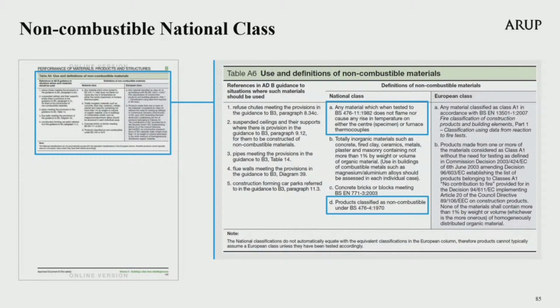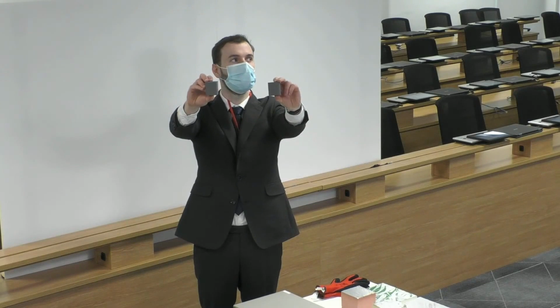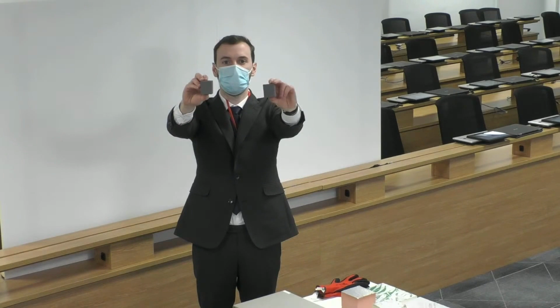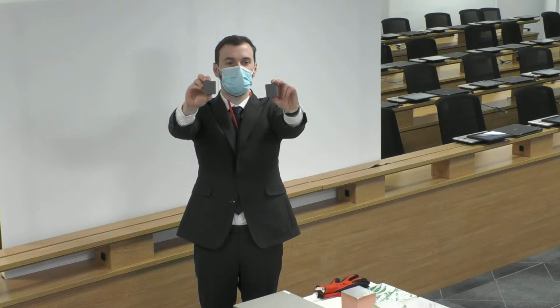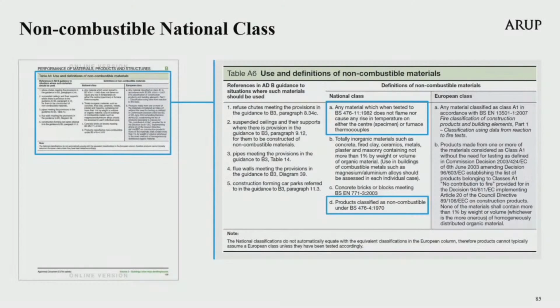Tom is holding up both samples again now as a reminder. The Part 11 test standard itself does not provide any limits on temperature rise or duration of flaming. Instead, these are set out in Appendix A only at point A as marked in the upper blue box. There, Table A6 states that the material, when tested to Part 11, does not flame nor cause any rise in temperature on either the specimen or furnace thermocouple. This is the national class for non-combustible also.